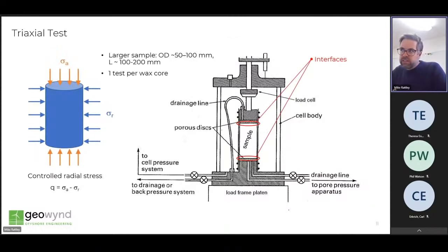The cyclic triaxial test then is performed on a comparatively larger specimen with a diameter between 50 and 100 millimeters and a length from 100 to 200 millimeters, i.e. a standard length to diameter ratio of 2. Due to specimen size, it's typically only possible to obtain one triaxial specimen per core, which makes the test far less efficient than the DSS test for intact core samples, with many more required to facilitate a test program.